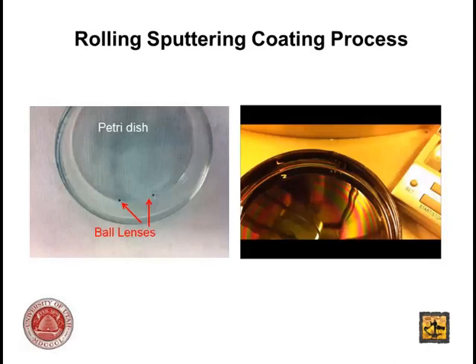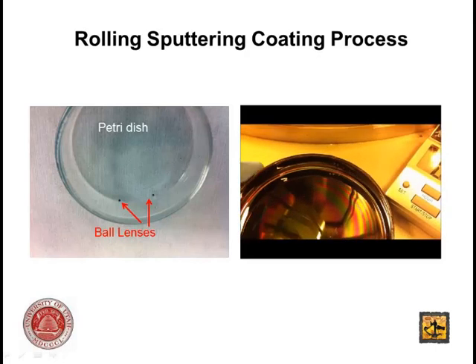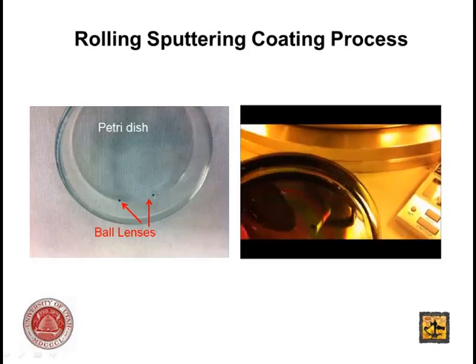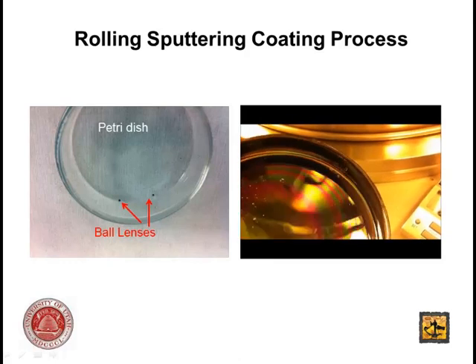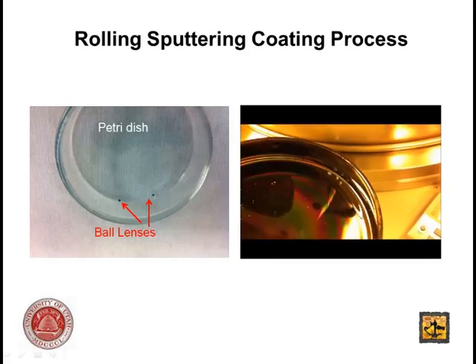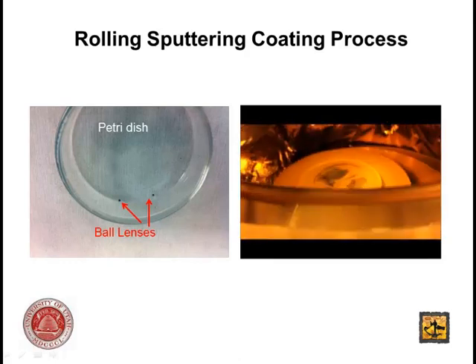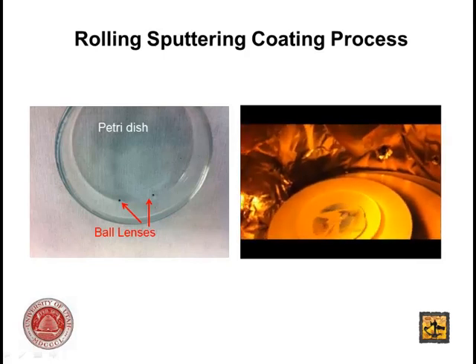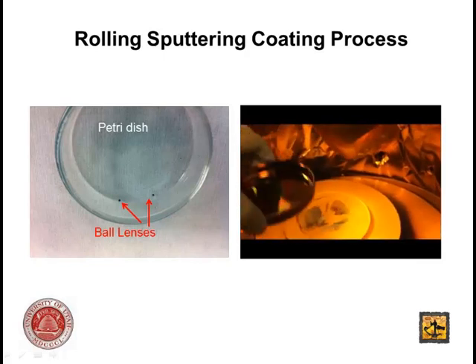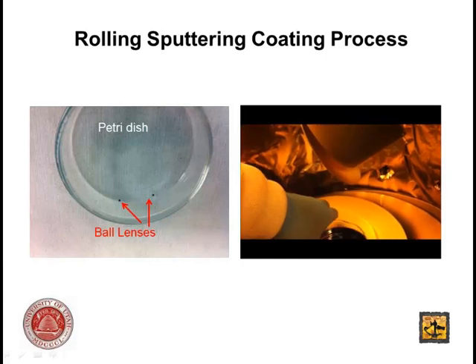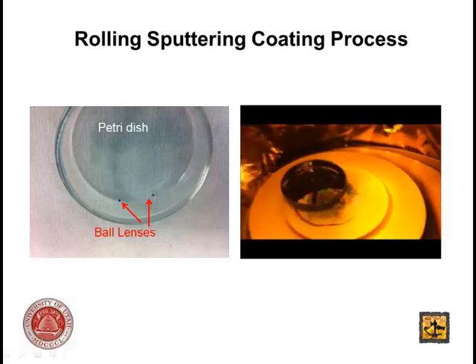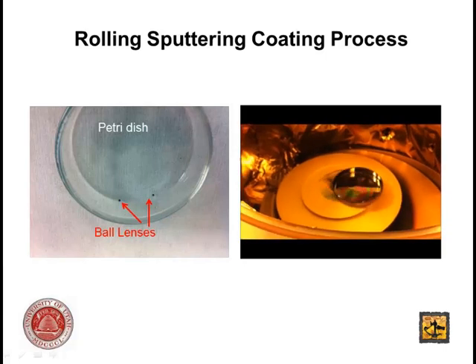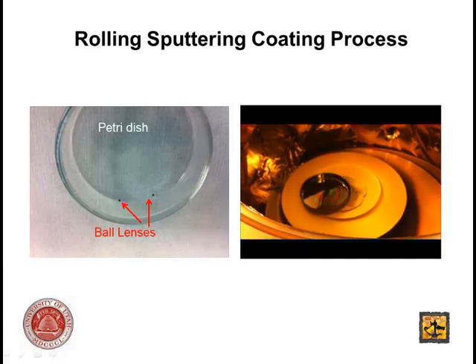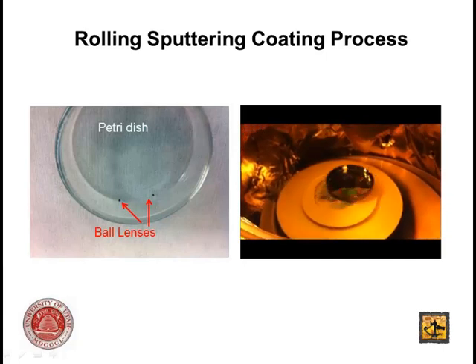The next view shows you how you do this rolling sputter coating process, which is really straightforward. We just take a few of these molds, these spherical lenses, you can see them out here, and they are moving. The idea is to put them in a container that rolls while the deposition takes place. That's the interior of the chamber of our sputtering system, which has a rotating stage. The way this works best is if you put that container in an eccentric kind of path, so the balls continuously keep rolling, for something like 2 or 3 hours. So you get a very uniform deposition. That's how you do it.